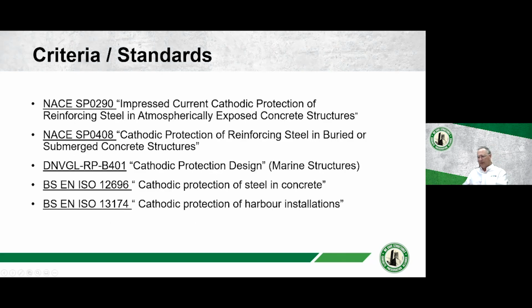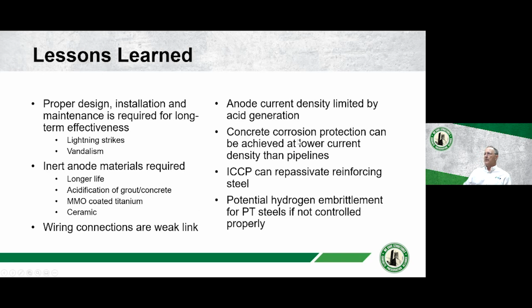I'm sorry, I've got to back up again. The concrete corrosion protection can be achieved at lower current densities than pipelines. That's another very positive thing. Initially, they were running these systems at a really high current density, very similar to pipelines, which are being protected by impressed current and galvanic systems all over the country.